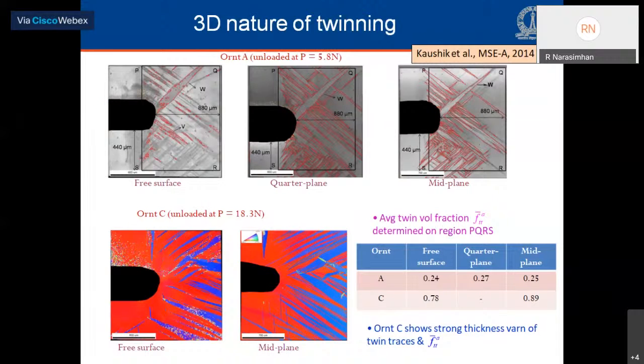Now, one of the things that we wanted to investigate, and this has very rarely been looked at in the literature, is whether some of these twins persist through the thickness. Do they have a 3-dimensional character? So in order to do that, we unloaded some of our specimens and then chemically etched and polished them down to the quarter plane and the mid plane, and then subjected the specimens to EBSD analysis.